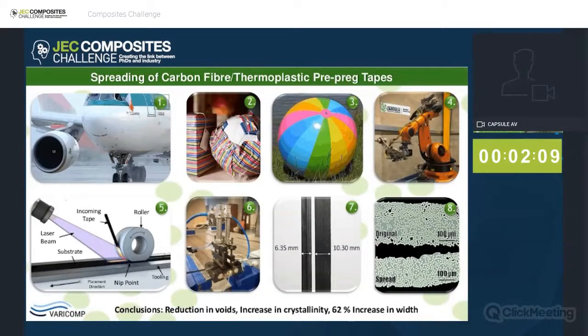How it works is that there is a heated platen with 2 compaction shoes. The carbon fiber thermoplastic prepreg tape is fed through the small device. The heated platen melts the thermoplastic resin, and then the compaction shoe applies a downward force on the melted resin and fibers. This squeezes the tape and results in an increase in width. We completed many different spreading trials, trying different processing parameters such as different temperatures, pressures, and pull-through rates. There were a lot of failed attempts, but we eventually achieved successful results where we were able to get an increase of 62% in width. Once we were happy with the spreading technique, we needed to investigate: does this spreading negatively affect the quality of the tape? We actually discovered that the spreading appears to improve the quality of the tape.